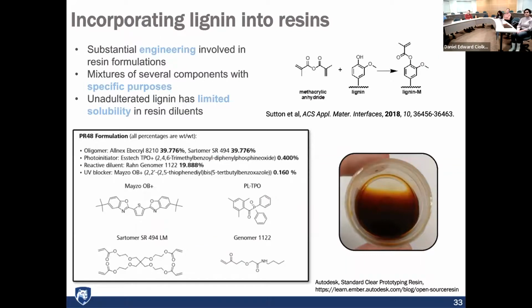And so there's lots of engineering that we have to do to incorporate lignin into resins. Primarily, we have to do that reaction. Remember, I told you there are these hydroxyl groups. We have to do chemistry there to put this on. I showed you before, it was what we call an L group, a linker group. It's for the polymer forms. That's this thing here. So this is what we call a methacrylate group. We can add these methacrylate groups by doing some chemical reactions. So we replace the hydroxyl H with this methacrylate, and then we can polymerize. That's what gives us this nice homogeneous mixture.